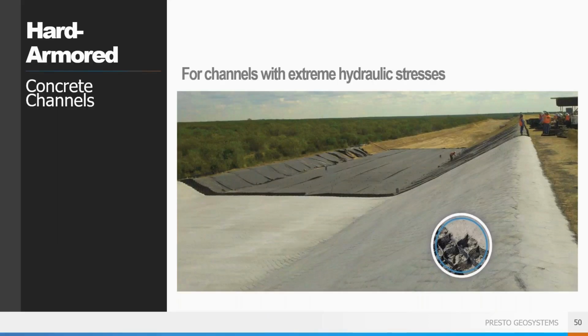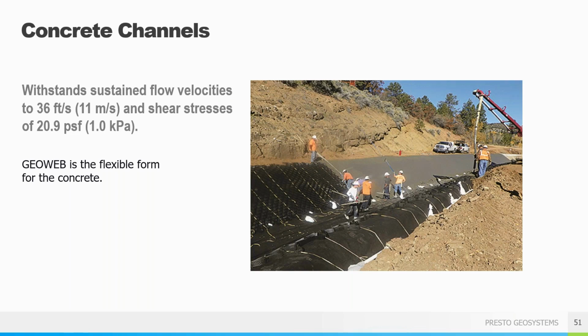And finally, for your most challenging applications, we can provide a concrete-filled GeoWeb. In this case, the concrete is going to be poured in place with no additional forms or reinforcement required, as the cell walls will function as both. And it will allow for easier to place higher slump concrete. It is a flexible system that will withstand settlement very well, which is of course quite important in landfill applications. And then we also assure uniform concrete depth, because you just fill right to the top of the cell walls. And typically we can replace a 5 or 6 inch depth of reinforced concrete with just 3-inch GeoWeb filled with the very same concrete.